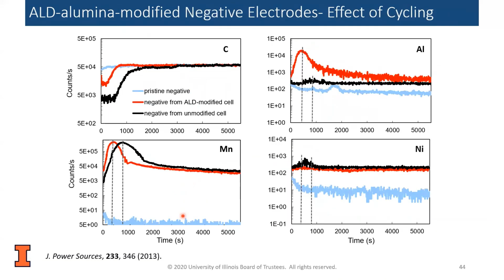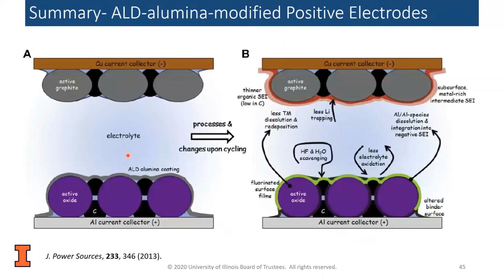And this is a comparison of the SIMS of the negative electrode that we see in the unmodified, the modified cell right here. We got a lot less of the migration. So in the uncoated film right here, we see that the depletion of the manganese goes pretty deep as compared to the depletion in the coated. So what we found here is that the alumina coating does initially prevent the dissolution of the metal, but eventually it'll break down.